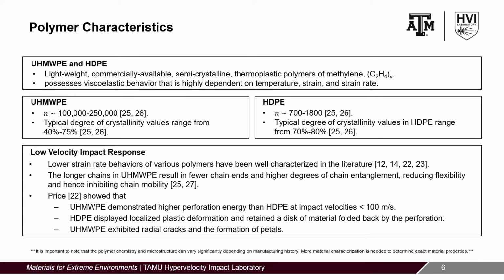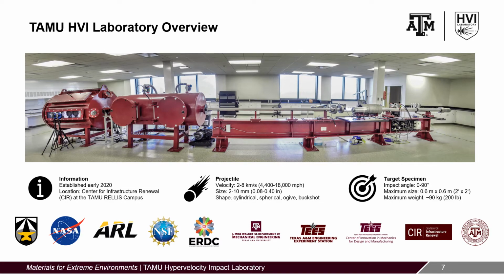At lower velocities, ultra-high molecular weight polyethylene demonstrated higher perforation energy than high-density polyethylene. It has also been shown in the literature that the materials have different damage morphologies at low impact velocities. Studies have also shown that ultra-high molecular weight polyethylene exhibited better hypervelocity impact performance than Kevlar, which is used in conventional Whipple shields. Achieving hypervelocities, which we will denote here as velocities greater than 2 km per second, is difficult in general, especially as the projectile size and mass increase.